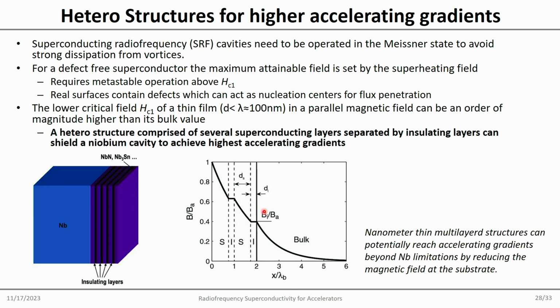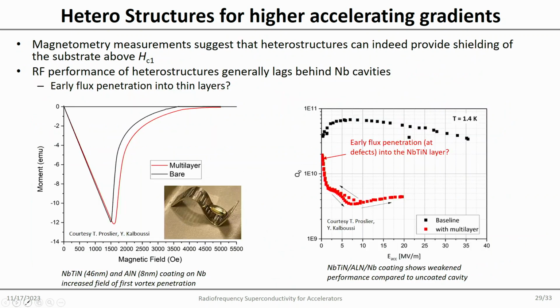Okay. So where are we with that? This is a magnetometry measurement. The straight line tells you perfect diamagnetism, and that would mean I am in the flux-free state. So I apply a field, and as soon as it starts to drop off here, this is where I go into the mixed state where I have fluxoids.